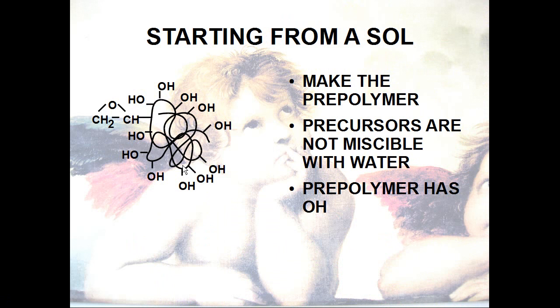Usually precursors are oils, not mixable in water, and very often a lot of people propose to use them dissolved in alcohol, but this kind of application is not for us, because we want a chemistry more clean, more safer. If we hydrolyze our precursor, the alkylic groups will be replaced by hydroxy groups, and hydroxy groups will give us more miscibility.